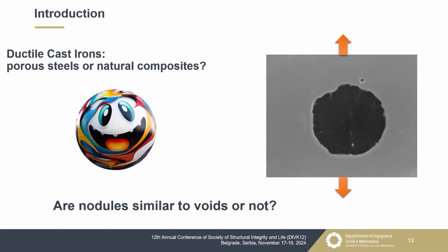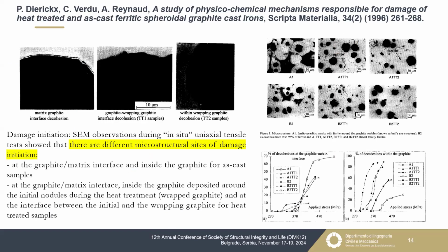But we also have some different results, some different approaches, and some of the authors stressed other damaging mechanisms. For example, in this case, the authors considered the different mechanisms that could be obtained in the as-cast ductile cast iron and in the heat-treated ductile cast iron. In the heat-treated cast iron, we have a supplementary shield around the previous nodule due to the diffusion of the carbon on the nodule. In this case, the authors found, as the main damaging mechanism, the decohesion between the matrix and the nodule.